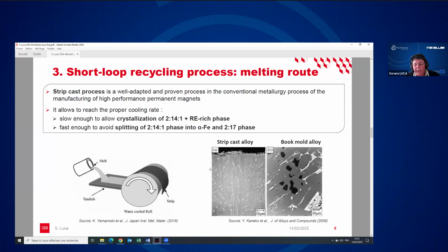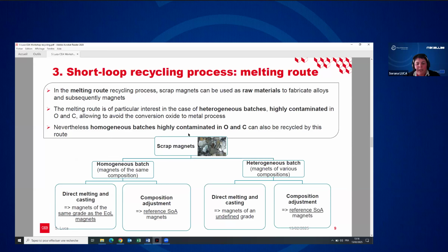Concerning the melting route, it is performed by strip cast process. The strip cast process is a well-adapted and proven technologies in the conventional metallurgy process of the manufacturing of neodymium iron boron high-performance magnets. The raw material is induction melted. The melted alloy is poured on a copper water-cooled rotating wheel. And alloy under the form of flakes of several hundred of micrometers are obtained, and these flakes have a particular microstructure which is very well adapted for the subsequent steps of the manufacturing process. And only the strip cast process allows to obtain this particular microstructure. So in the melting route, the scrap magnets can be used as raw materials to fabricate alloys and subsequently magnets.